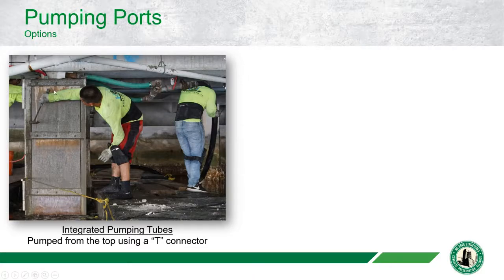So in this example here, we have an 8-foot jacket. There are ports within this pumping tube that automatically flow out as the grout starts to rise. It creates pressure within the jacket and then creates the valve, essentially. So it allows the grout to go down to the bottom of the jacket.